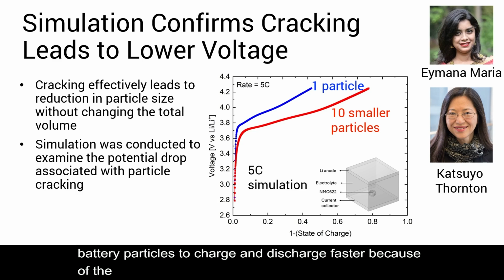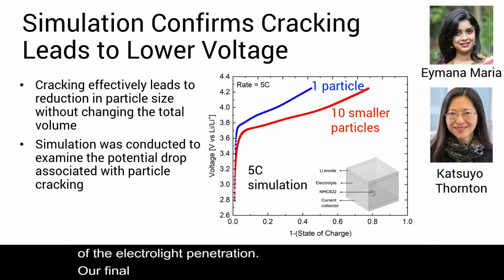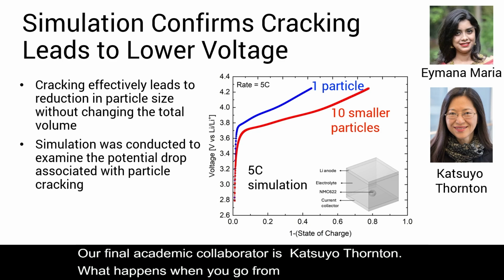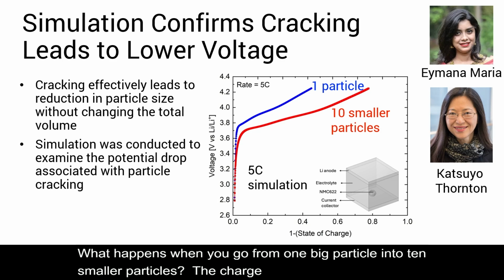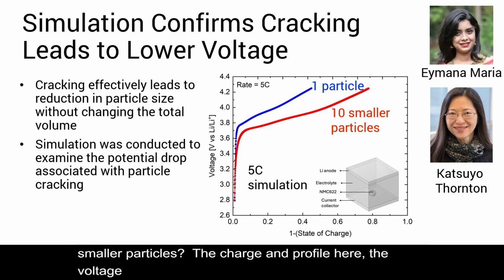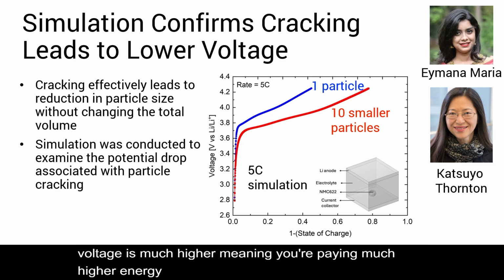So our final academic collaborator is Professor Katsuyo Thornton and her student Eymana Maria, who I believe has a poster over there as well. And so they did some simulations, basically seeing what happens when you go from 1 big particle into 10 small particles. And what they've shown is that if you go from 1 big particle, the charging profile here, the voltage is much higher, meaning you're paying a much higher energy cost if you have 1 big particle before cracking as opposed to 10 smaller particles after cracking.